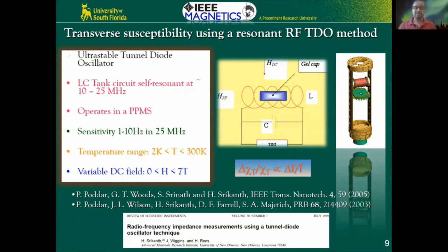Since it's a resonance circuit, all we do is monitor the shift in the resonance frequency, and from that we can get a change in the transverse susceptibility. I'll tell you why transverse in the next slide, but here's why this is a very good technique: the sensitivity is very high. All we do is measure the shift in the resonance frequency. You can use a frequency counter to measure the frequency. By the way, those who are experimentalists should know that frequency is perhaps the most accurately measurable quantity.